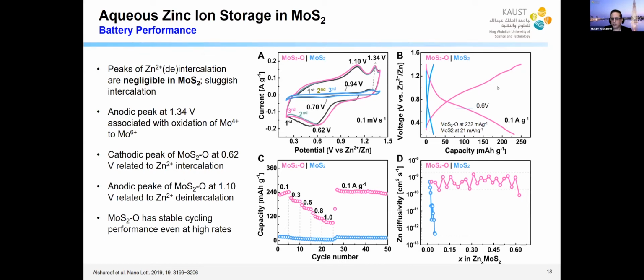If you look at the charge discharge curve, okay, look at the pink. The capacity is about 200 milliamp hour per gram. And look at the blue, the capacity is under 40. Hardly any zinc goes in the molysulfide, but with this simple oxygen substitution, you can essentially have an order of magnitude increase in the capacity. This is reflected in rate performance. You see the pink here in C is actually recovering completely to the initial capacity after cycling at higher current. And then the blue one, which is molysulfide without oxygen substitution, has very low capacity. And this is the corresponding zinc diffusivity in the two materials, showing that it is substantially more mobile in the oxygen substituted molysulfide.